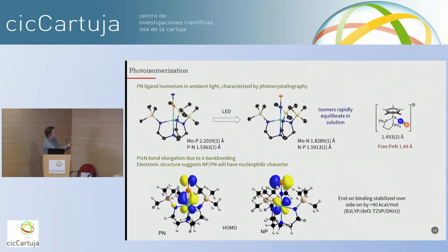So we did a single crystal experiment where we irradiated this complex in the X-ray diffractometer, and then in the dark we collected data, and then we irradiated again and collected data. We could see that this slowly isomerized from PN to NP. If we look at the bond metrics, the PN bond distance is actually a little longer for the nitrogen-bound isomer. And if you look at the frontier orbitals, the HOMO is a very nice back-bonding orbital from a molybdenum d orbital into the PN pi star orbital. We don't know exactly how this works mechanistically, but if you try to flip this sideways using DFT, the barrier is pretty high. So I'm not sure exactly how the isomerization works.